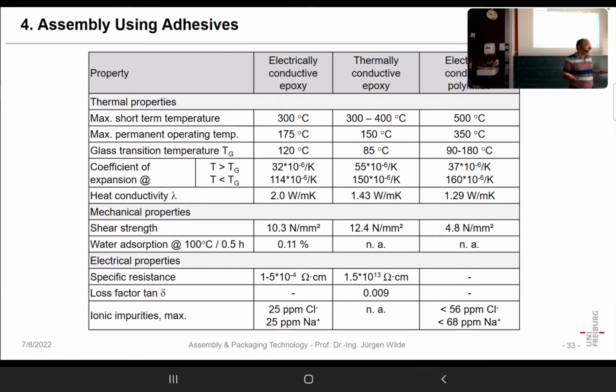That is important because when you have not just humidity but moisture, then ions can be dissolved and the ions will become conductive, and by conductivity you can have problems, high resistance circuits, like some FETs or so. They can have already problems due to creep currents.